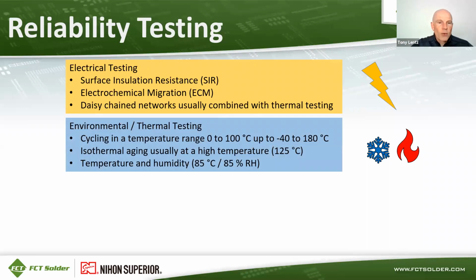Then, of course, environmental and thermal testing is the most popular type of testing that we do to measure reliability. Temperature cycling is well used, and the ranges can vary from 0 to 100 C up to -40 to 180 C, which I heard an automotive component supplier talking about recently. That's going to be a new testing protocol for them, which is quite an aggressive and extreme temperature range. Isothermal aging can also be done, usually at elevated temperatures like 125 C. And in some cases, we might combine high temperature and high humidity in order to stress those electronics in a different way.